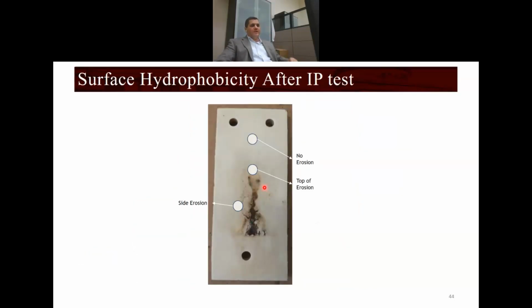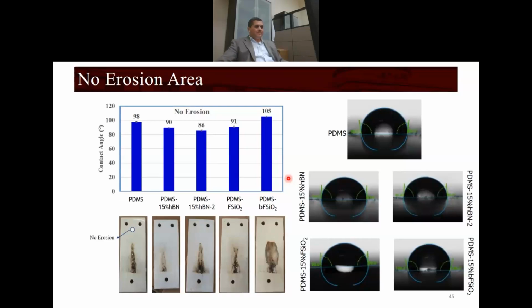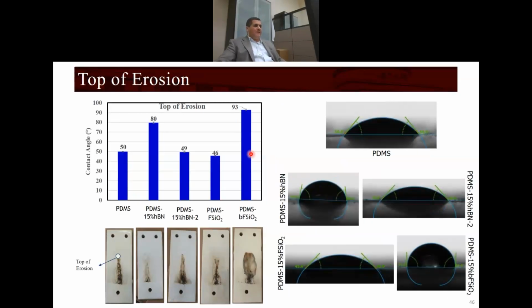Then we analyzed the hydrophobicity, what happened to the surface hydrophobicity at 3 different spots: the side of the erosion, an area where there is no erosion, which should be very similar to the contact angle before the erosion, and the top of the erosion point. In the areas where there is no erosion, you see the contact angles stay the same for all the samples. No change happens in those areas. The biggest change happens in the area where the erosion happens.